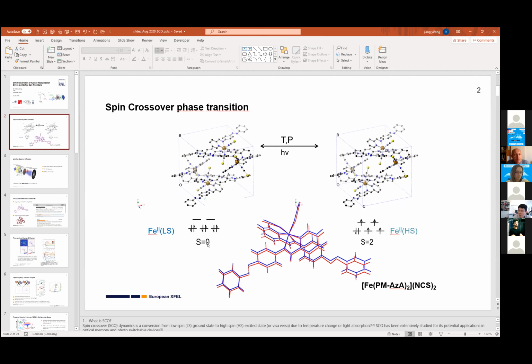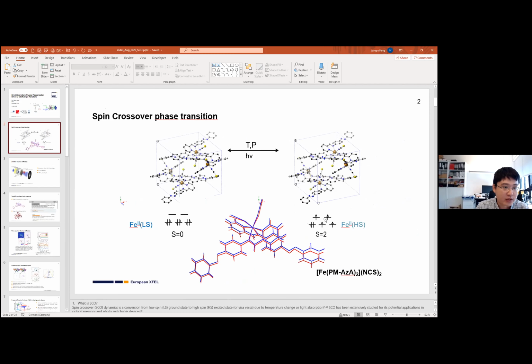So in the spin crossover, one of the direct structural results is the iron nitrogen bond elongation. The reason is, like I showed, two paired electrons in the low spin state, and one goes to the anti-bonding orbitals and becomes unpaired. So it's breaking the pi back bonding from the nitrogen. In the end, the coordination bond is weaker, and that gives us the iron nitrogen bond elongation. This is the reason why we even see a structure change in spin crossover. And in many works, it has been shown to be around 0.2 angstrom iron nitrogen bond elongation.